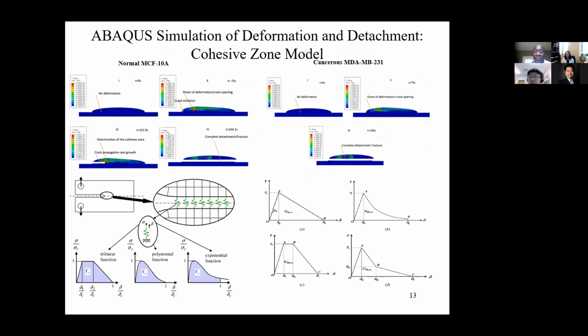So one can now use this information to model the contributions of these bridging filaments to the opening process. So one can take all this and now turn these into models that essentially idealize the opening and the shear deformation of the cells in finite elements. One can also introduce cohesive zone elements to really model the opening and cracking process that is associated with the detachment process. And similarly, one can do cohesive zone models where you use measurements of the true adhesion energies to determine the cohesive zone parameters.